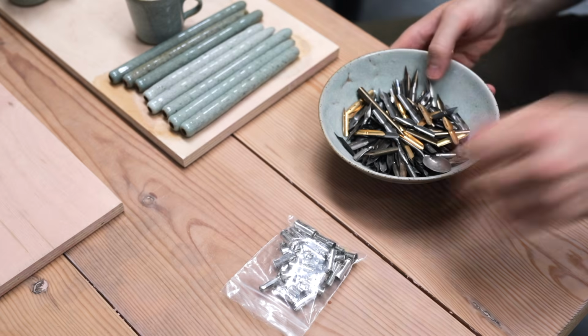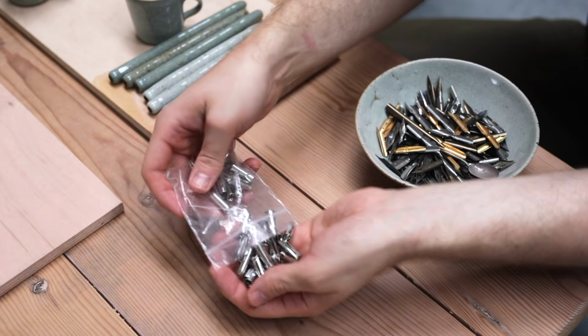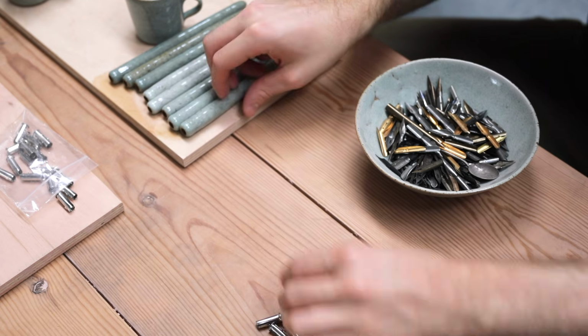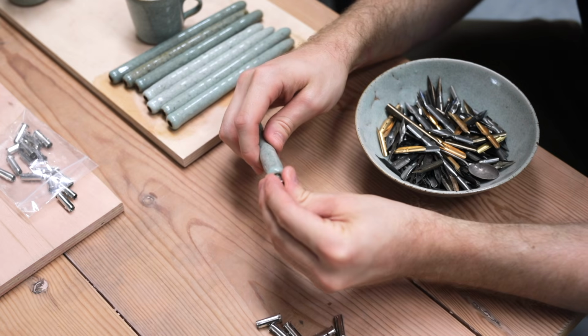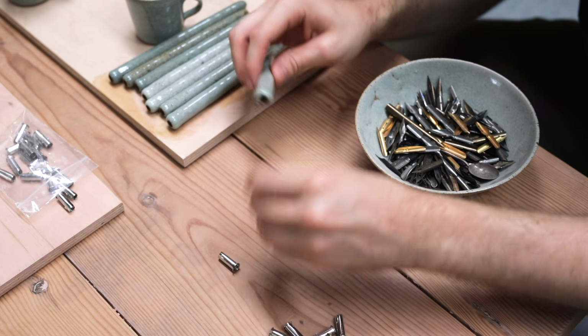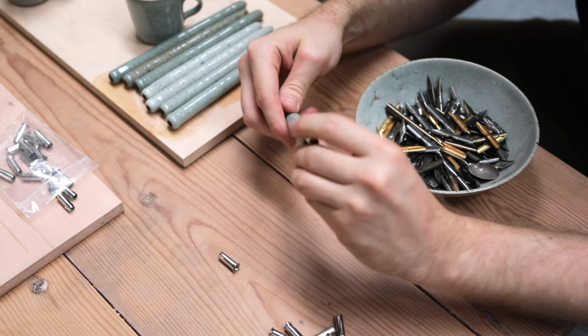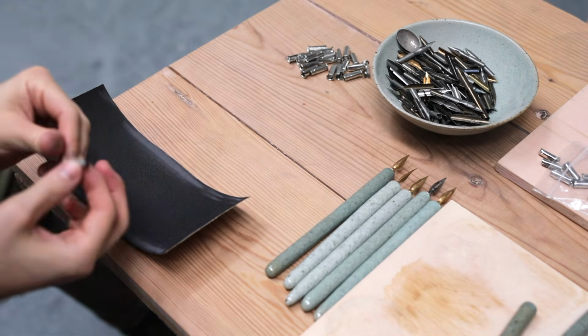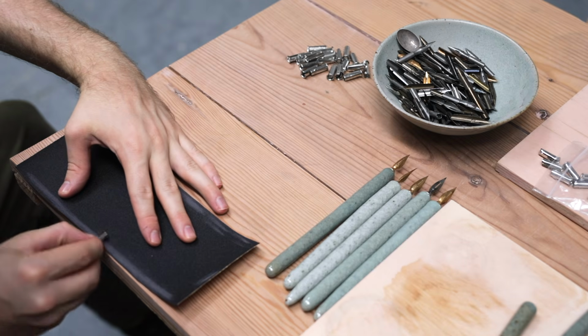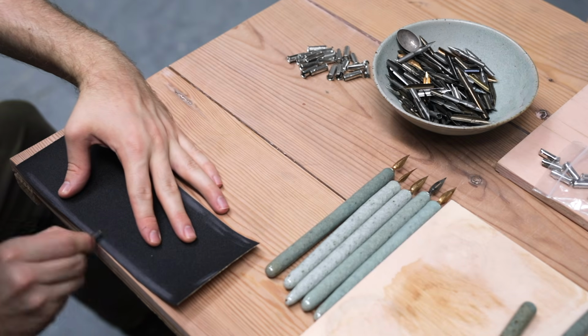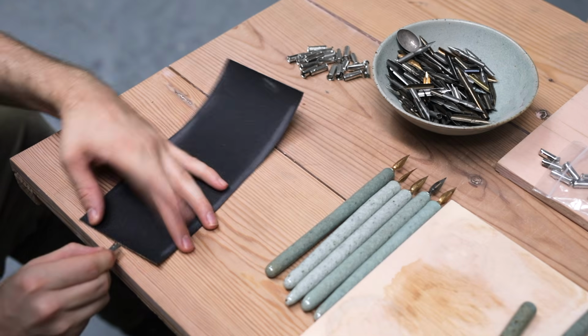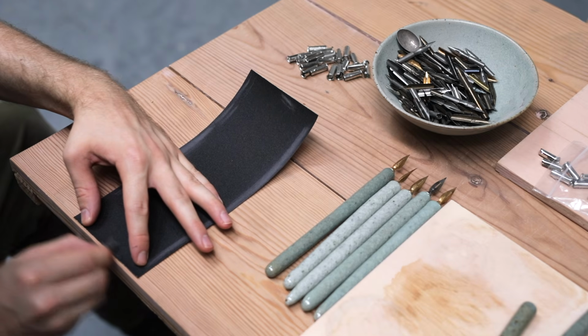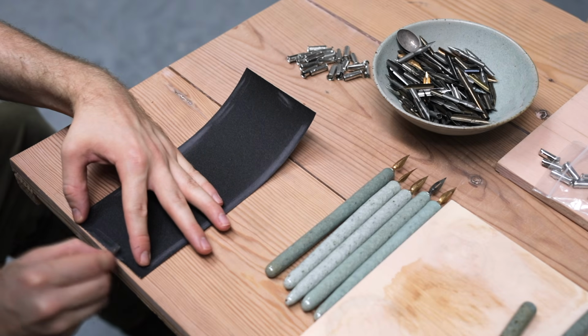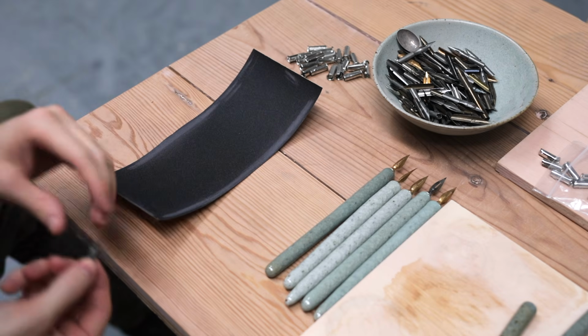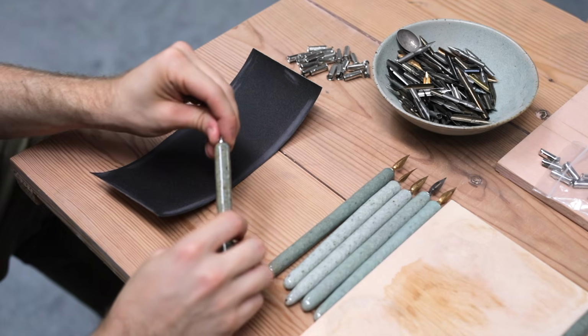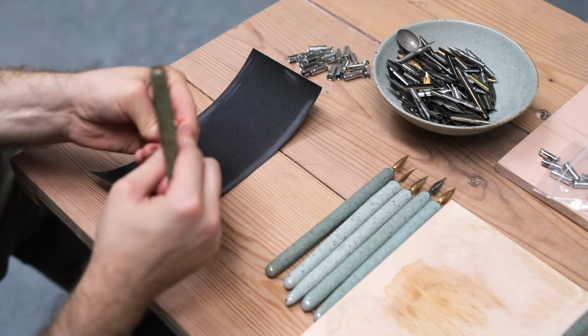The ferrules go in quite easily. Generally, I think these metal pieces are produced for wooden dip pens. They have a little metal spike that pokes out of the ferrule, I think, so that when you insert it into the wood, it's locked in place. Ceramic, on the other hand, has no give, so the spike actually stops it from going in altogether. So I simply sand it away and squeeze the ferrule to be a bit tighter, if need be, until it fits in. Sometimes they can be a bit tight, but I figure it's better they're more secure, rather than being loose and not fitting at all.